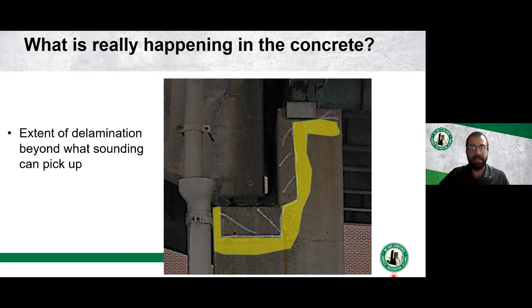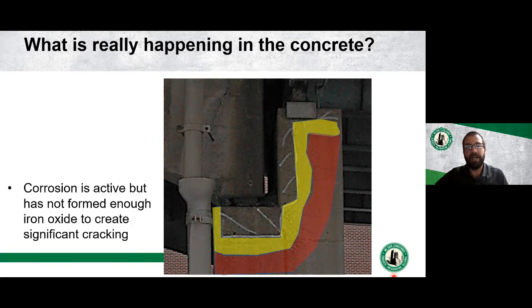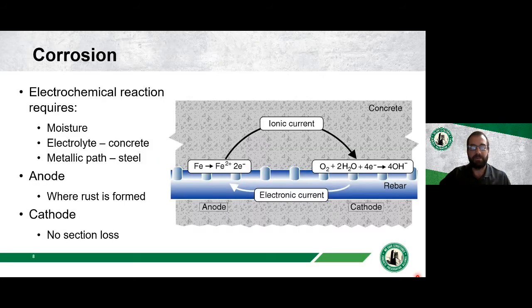And then at the end of the day, it's probably going to end up being the white area and that yellow area. But if we just go out and repair the white and the yellow, are we really addressing the structure fundamentally? Could there be areas of corrosion beyond that repair area that are active but have not formed enough iron oxide to cause cracking or delamination of the concrete? So this red area represents potentially areas where there's active corrosion, but that corrosion is pretty young, and so it hasn't created enough damage yet to really necessitate a repair. But if we only go out and repair the yellow and the white, are we really preserving the structure for the long term? Or will we have to come back in 5 years and repair that area in the red as well? So that's what I'm going to be talking about today: the corrosion, how it affects deterioration, and evaluation of that corrosion.